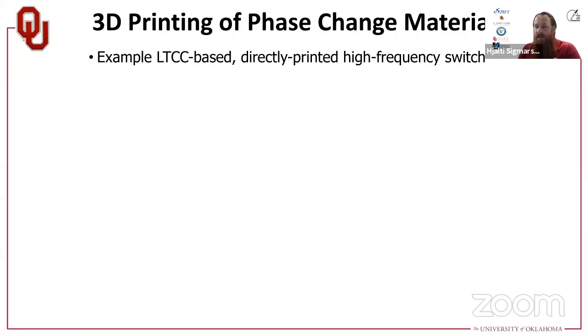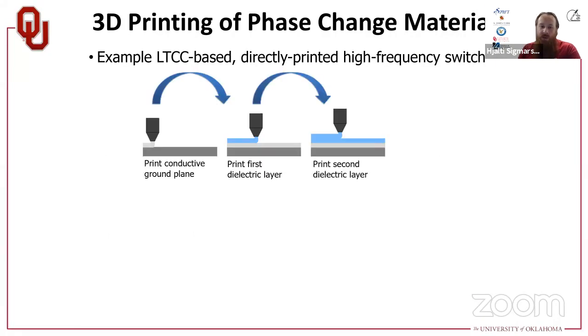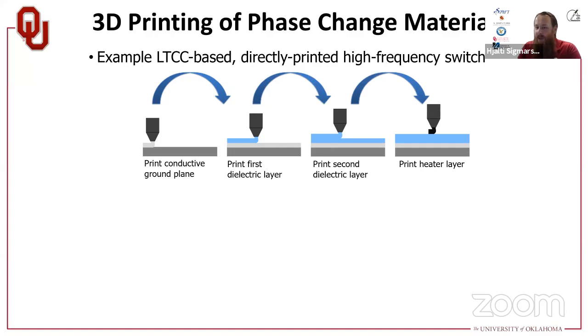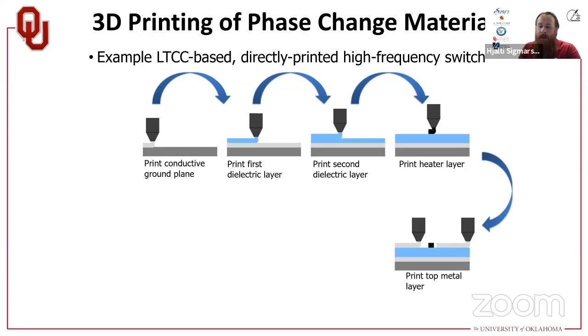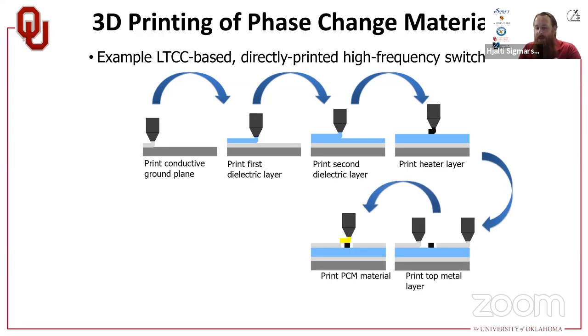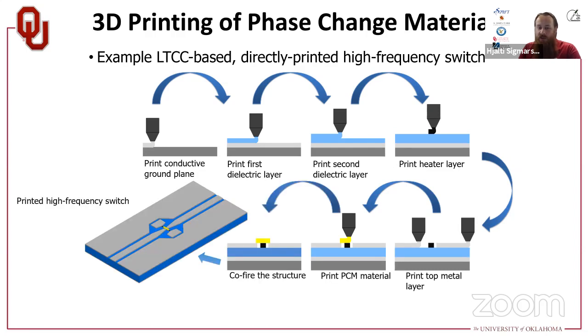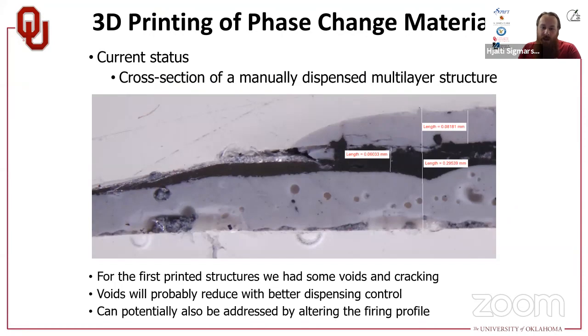Okay, so if we had a good material and we wanted to build a switch, we could just go with our regular printing process. Now we add a heater paste, maybe a tungsten-based paste, and then we would build our PCM, or phase change material, on top of that, and then fire the structure and end up with something like this. It would be like a typical RF switch, which allows us to either block the energy or pass the energy, which would be really nice. So we made some structures.